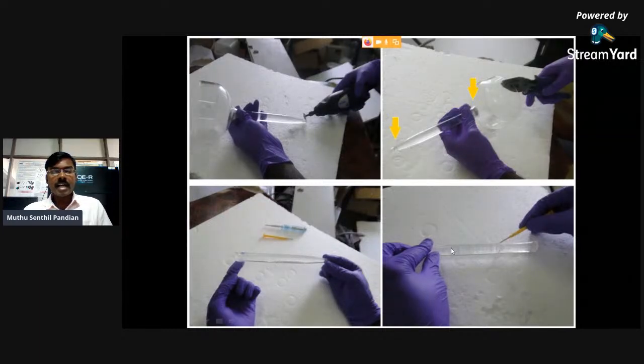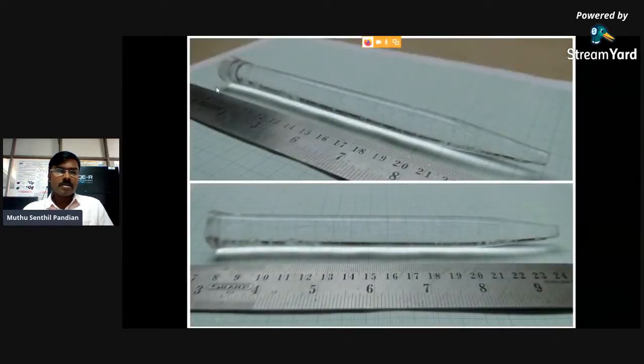Then using the diamond glass cutter, we have to mark the top and bottom portions separately. We have to do it very slowly and very carefully, otherwise cracks will form in the glass sample. Then using a sharp knife, we have to remove the glass very slowly. So this is the 15 centimeter long TGS crystal without the glass sample.